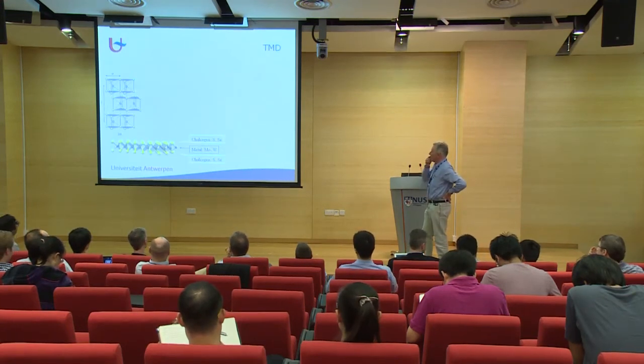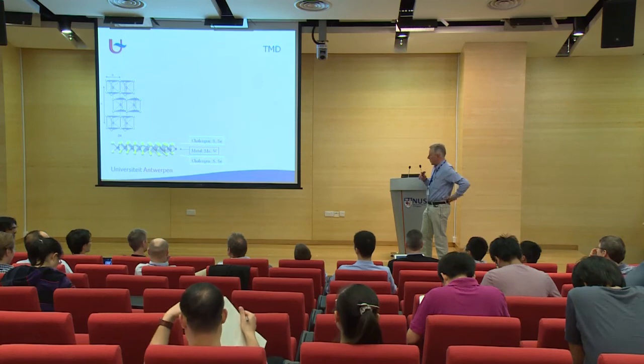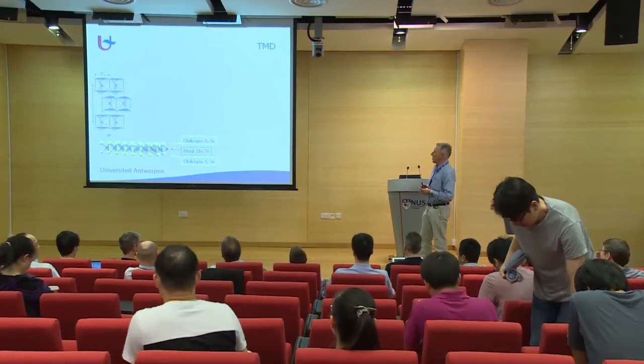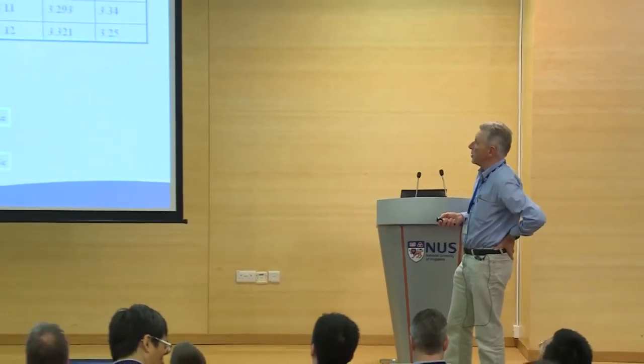So let's first give you a few simple facts about transition metal dichalcogenides. You have a metal layer here, and then on top and at the bottom of it you have the chalcogenides. For example, this is molybdenum or tungsten, and the crystal phase is this 1H phase, while if the metal is, let's say, titanium, vanadium, tantalum, it's typically the 1T phase. And the difference is simply, if you look at just the triangles here, they are rotated with respect to each other.